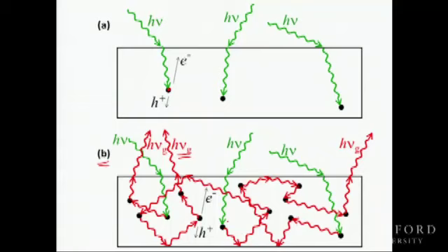Unless you've done that, you're not going to get close to the theoretical limit. You won't get past the 25%. And it's very counterintuitive, because normally we think, oh, fluorescent photons, that's a waste, that's a loss, but it's not. It is exactly what you need to get the highest efficiency. In fact, that fluorescence is kind of like a measure of the internal voltage.